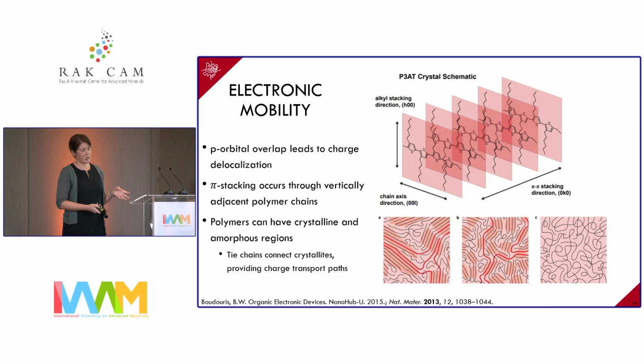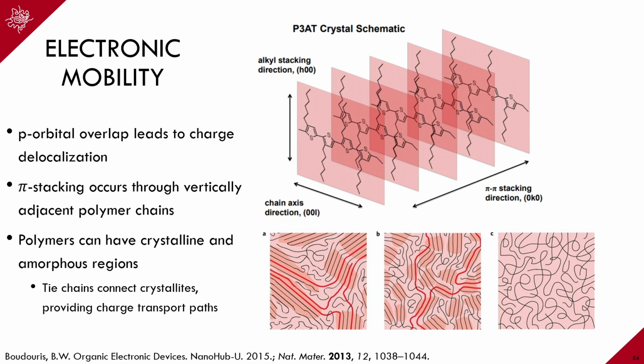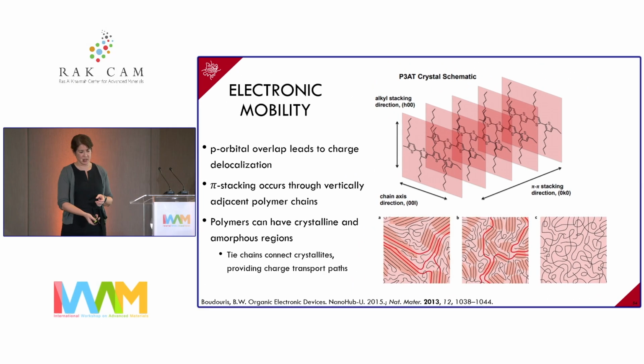So based on this semicrystalline film, the cartoon diagram that we all draw, the picture I show here has been our general understanding of how charges move through these materials. So you have these crystalline domains again, and in the crystalline domains, your chains are linear, they're planar. You have fast charge transport along the chain and fast hopping in the pi-pi stacking direction. And because we've always assumed that this is where charges move through quickly, the general design criteria for high charge mobility materials has been to design for high crystallinity. So we try to maximize crystallinity as much as possible. But because we weren't able to see this, we wanted to try and visualize some of these things.